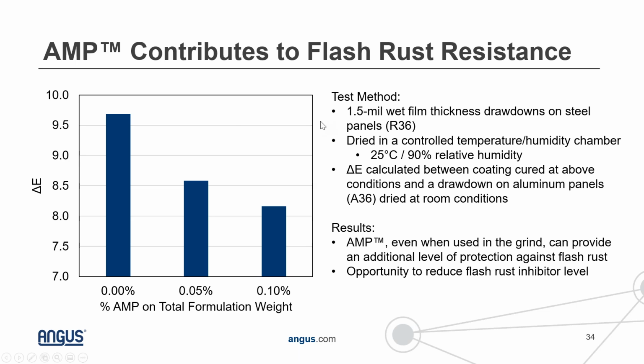And so we quantified that by looking at a delta E, so a difference in color between those samples that showed a general flash rusting. So the iron from those samples generated a more reddish brown color in the coating that could be picked up using a color meter. And we compared that to similar samples that were dried under room temperature conditions. And so we see that there's less of a color change, less flash rusting associated with higher use levels of AMP. So there's also potential opportunities to optimize or reduce the amount of flash rust inhibitor used in the formulation that contains AMP as a codispersant.